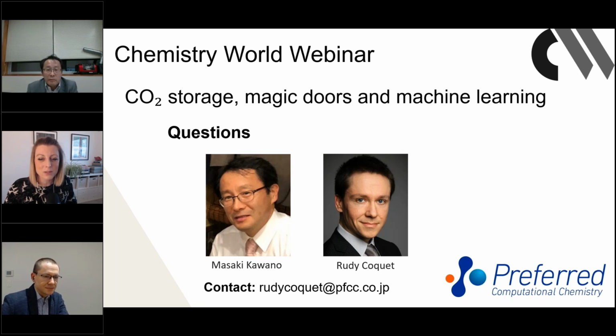We have a question: with high speed and accuracy, do you think Matlantis will replace density functional theory (DFT) methods? No, we don't think this is going to replace DFT. One simple reason is that we are not explicitly representing electron density in our calculations. Although this is not needed in many cases, in some cases you still need to represent, for example, a band structure, or calculate atomic charges very precisely, which you can do with Matlantis only as an estimation. So we believe DFT will work hand in hand with Matlantis. Matlantis can do the heavy lifting before the DFT part, screening thousands of configurations. Once you find an interesting one, you can submit that to the codes you run with DFT. That's how we see it.